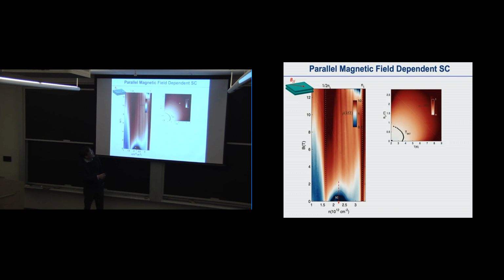If I chase 50% of the transition temperature, it looks like this. If you do a more quantitative job with the BKT transition temperature, it also shows this: at very low magnetic field, you start to see that superconductivity is actually enhanced with applied magnetic field. In-plane magnetic field somehow increases the TC. That's a very strange statement to make, since usually magnetic field always tends to kill superconductivity. So what is really happening here?